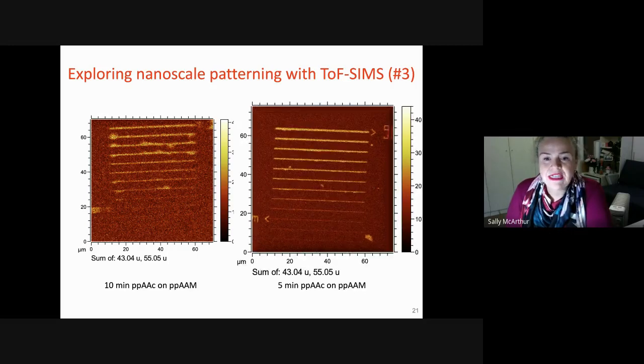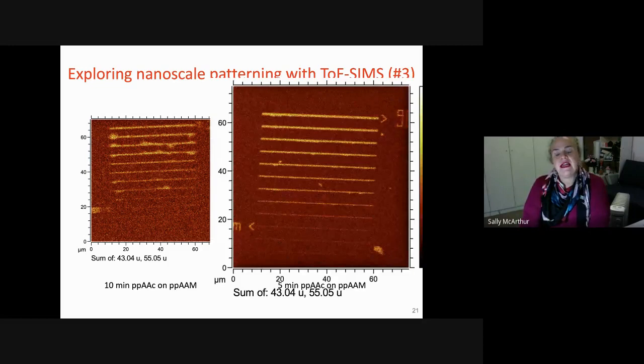And the really interesting thing with all of this is that we're able to demonstrate chemistry differences. So what this is actually looking at in these images are fragments that are associated with the acid-containing chemistry on the surface. So the acid pattern is the lines. The background is allylamine, and we've got data that shows that that is absolutely still allylamine there in the background.